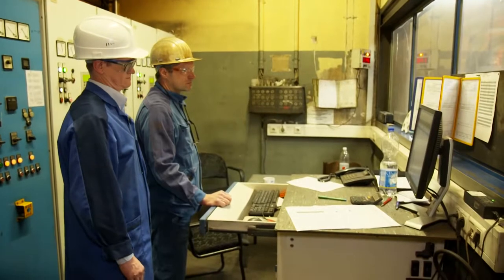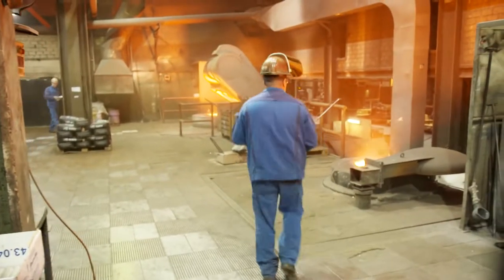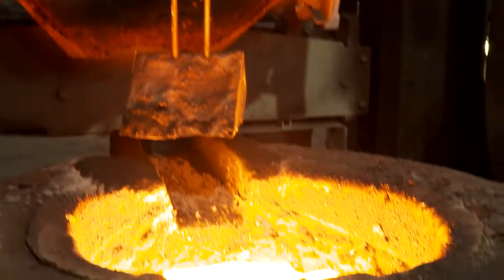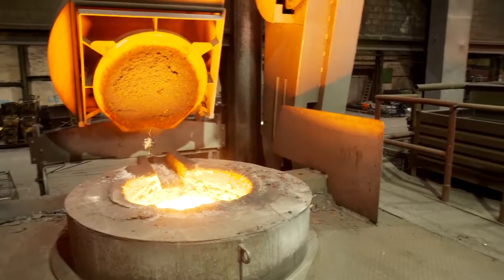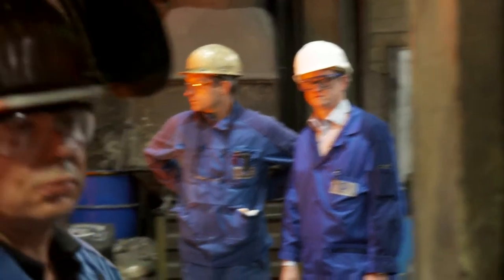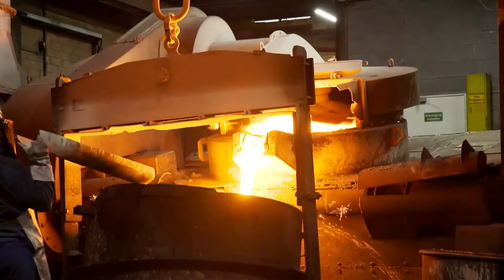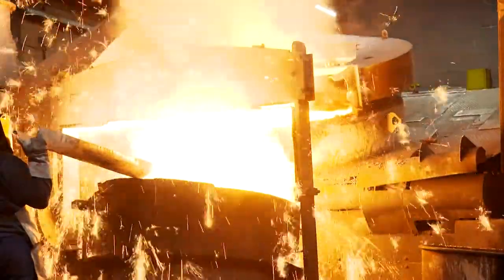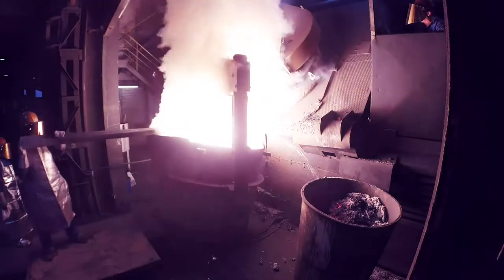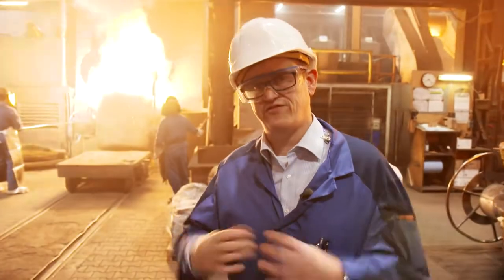The smelt has the perfect composition when the sample cools down in a certain way and then heats up again. The enormous heat is no longer generated with fire but with electricity — similar to an induction cooker, but the three electric induction furnaces in the foundry have the power of 5,000 microwave ovens. Their four megawatts heat the molten metal to over 1,500 degrees. The steel workers then transfer the molten mass, adding the final ingredient — magnesium — via chutes. At temperatures over 1,500 degrees, magnesium vaporizes rapidly, causing the bubbling sound heard during the process.